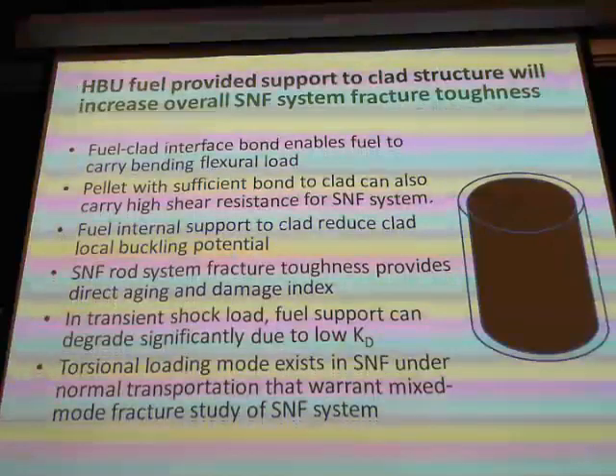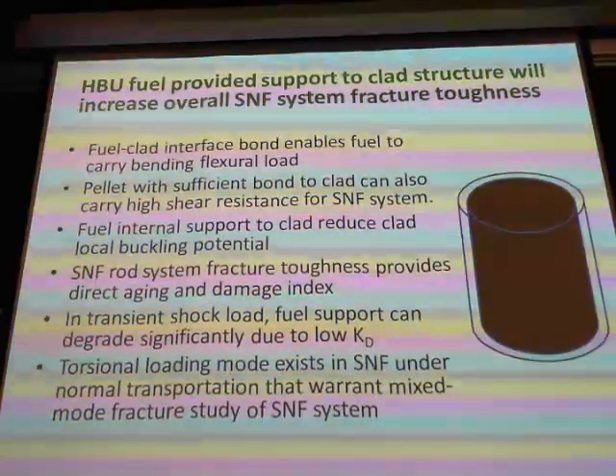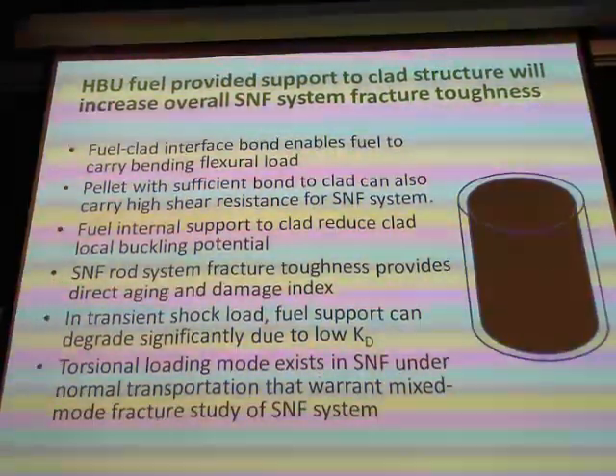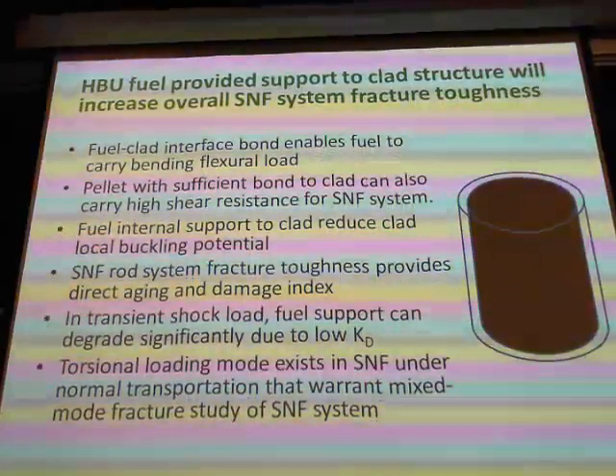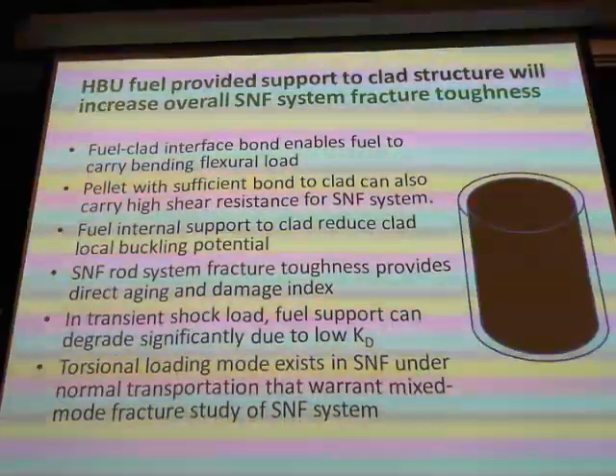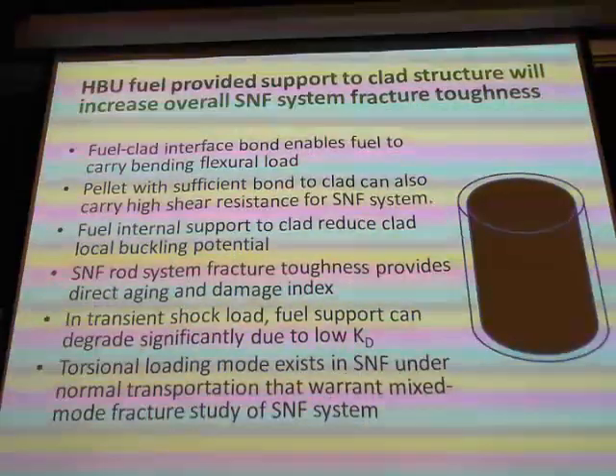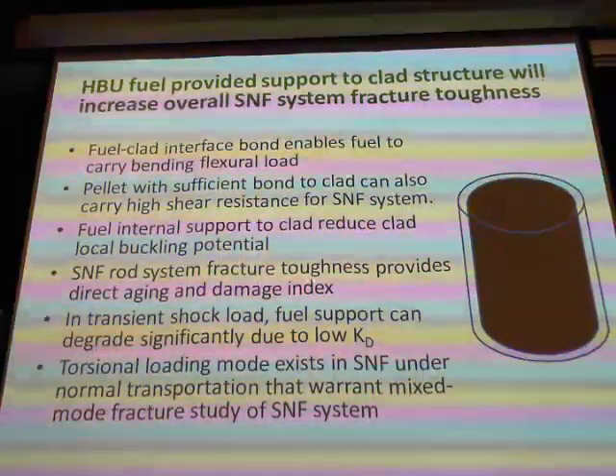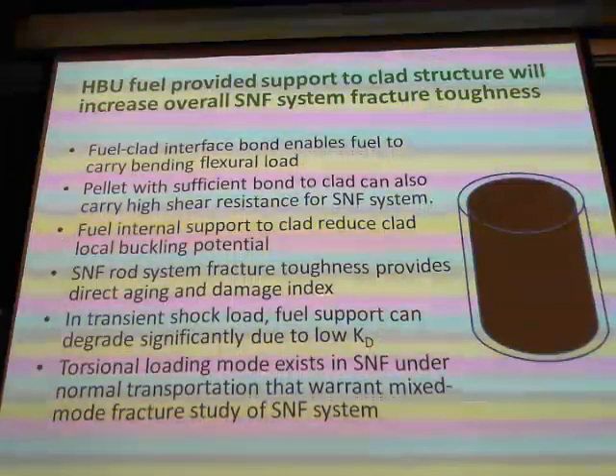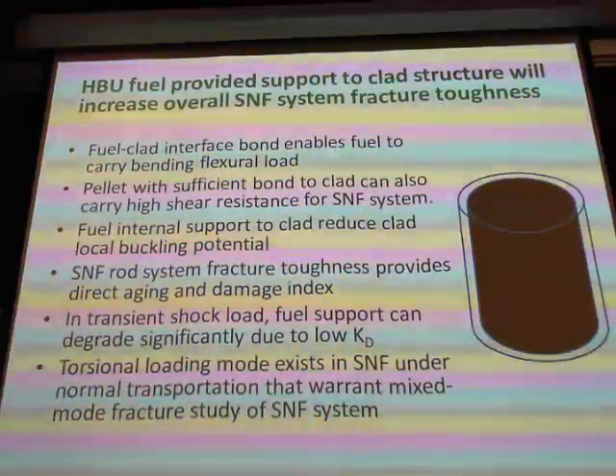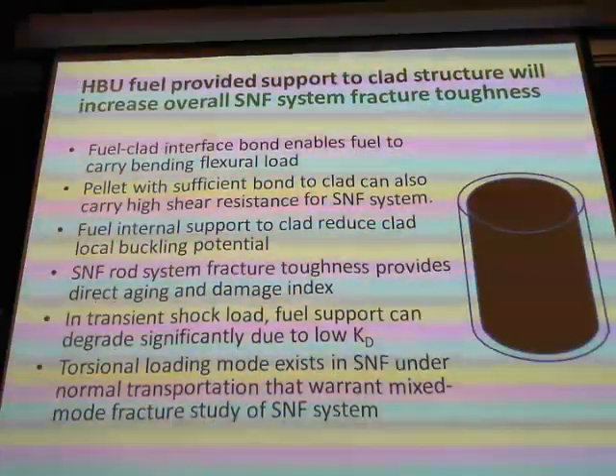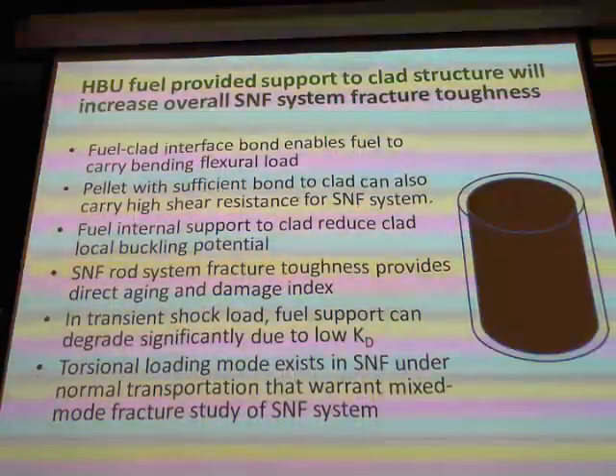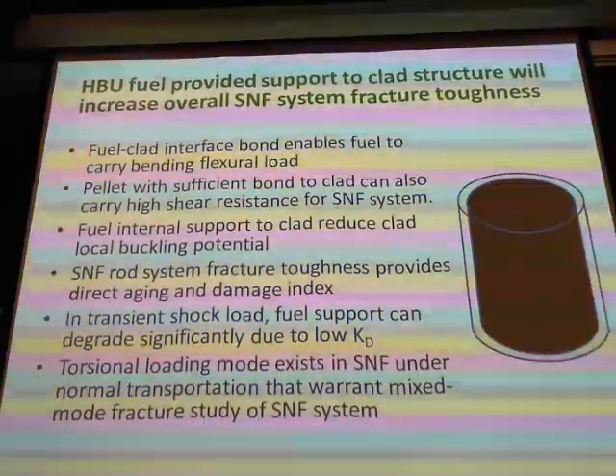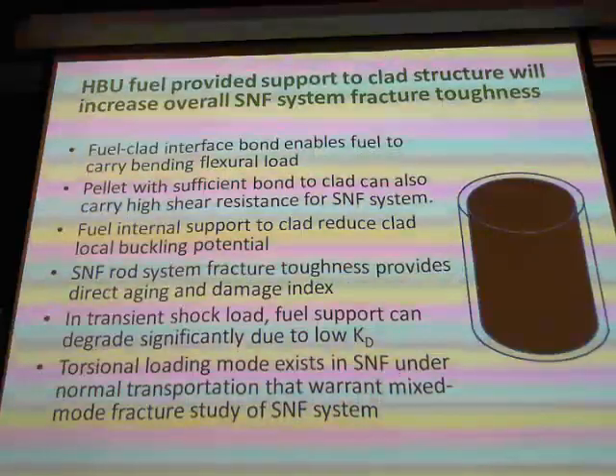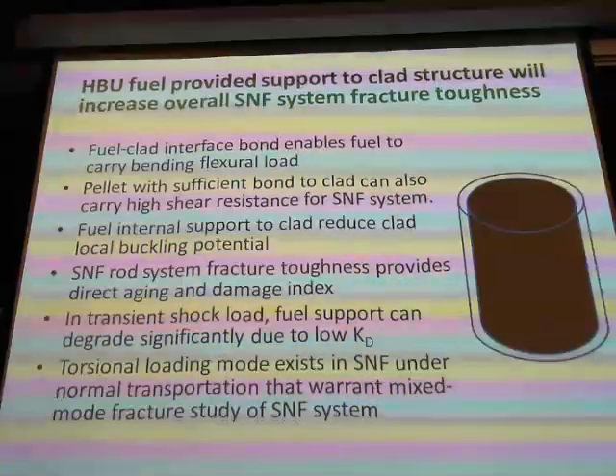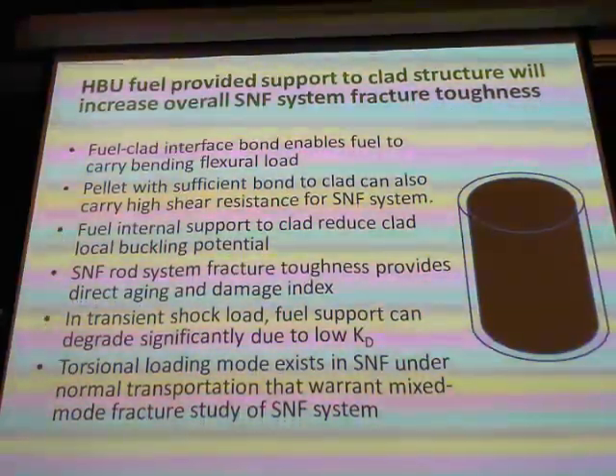And fuel internal support to the clad reduces clad local buckling. It's very important. You want to avoid the complication of local buckling. Fuel in there helps you to mitigate this. And the rod system fracture toughness provides a direct gauge to damage. I cannot emphasize enough: we do not have enough fracture toughness data for spent fuel cladding structure, for tubing structure. So new thinking, new approach is needed.